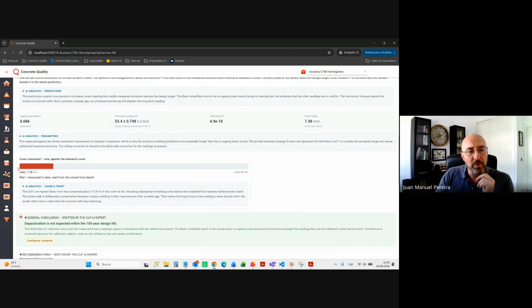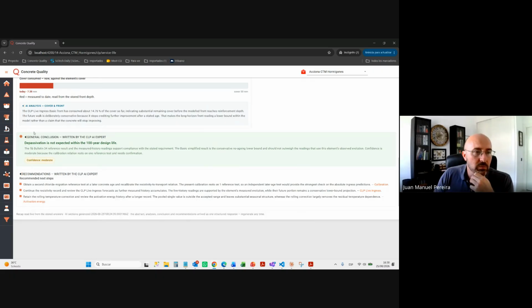It gives you how much of the cover is consumed today. This is a real indicator that you can test. You can go and take a core drill of your structure now and see if this matches. If it doesn't, you can input that result as well and readjust the prediction. So in the end, it will give you a conclusion. In this case, the depassivation is not expected, so it will meet the 100-year design life. It has a moderate confidence here because it has only one test for the chloride diffusion, so it recommends that you have more, and it gives you the recommendations here.